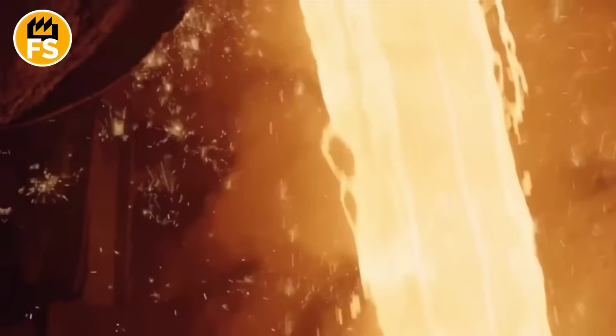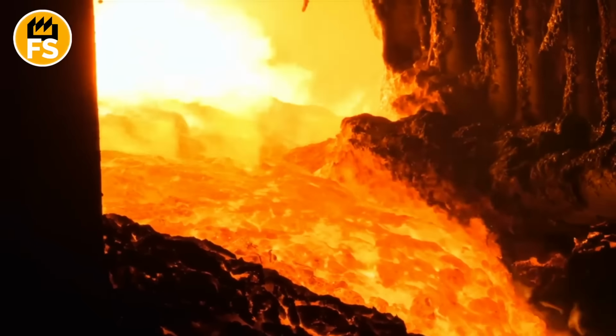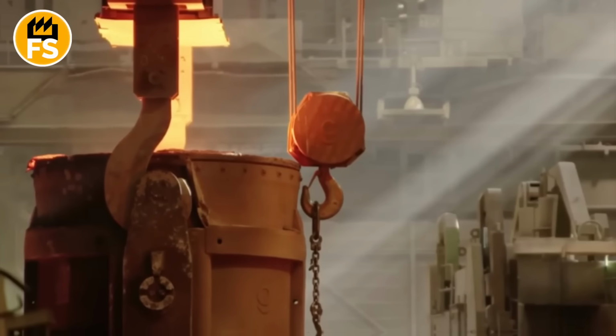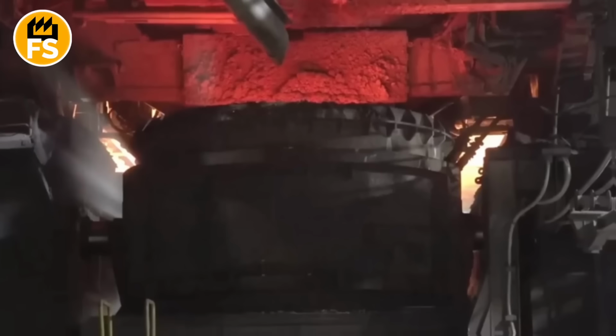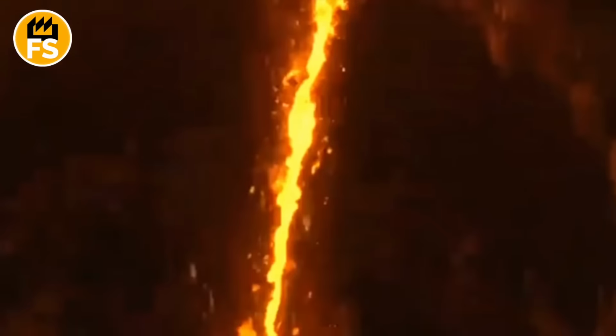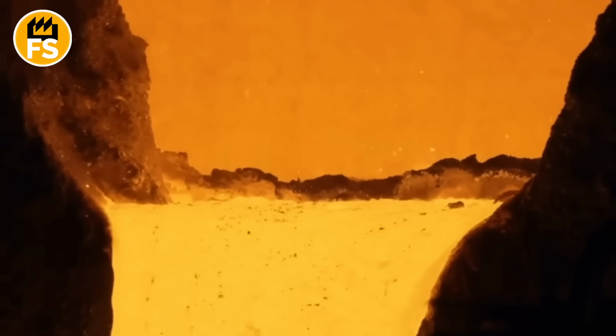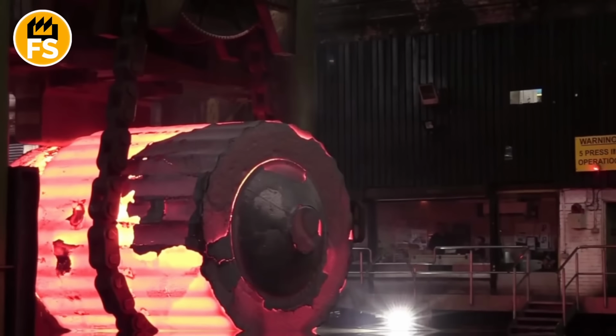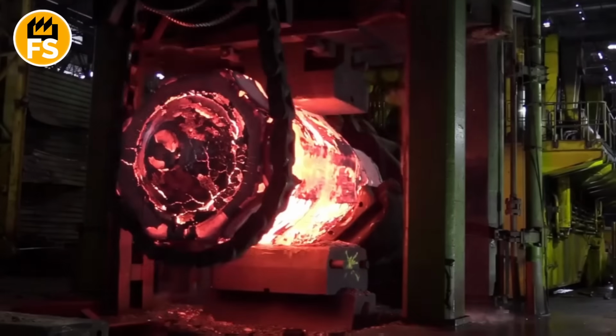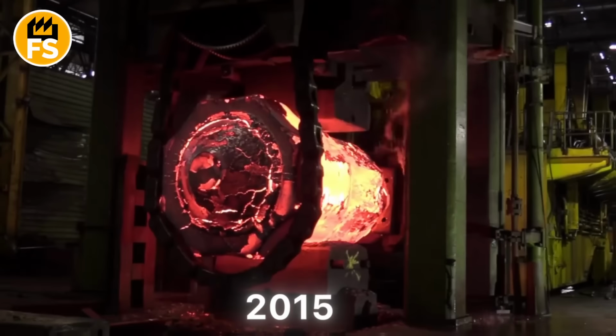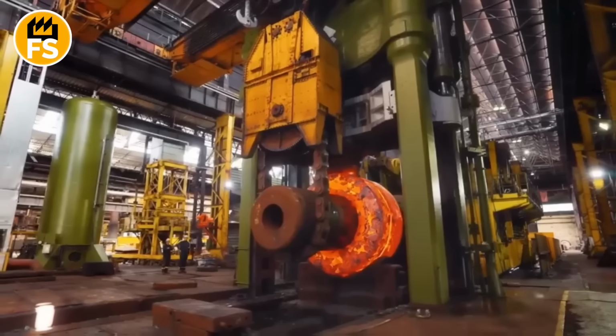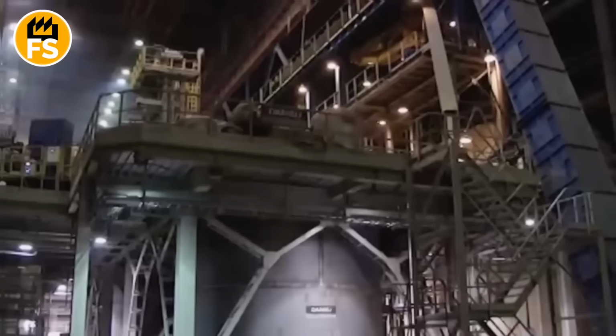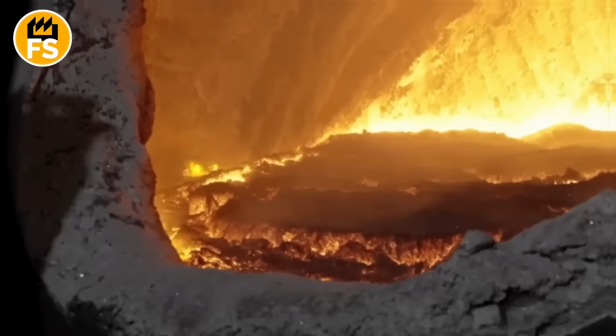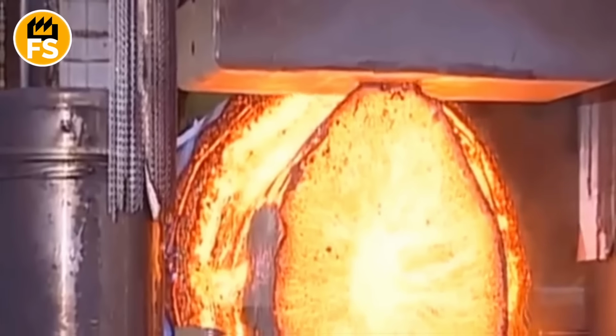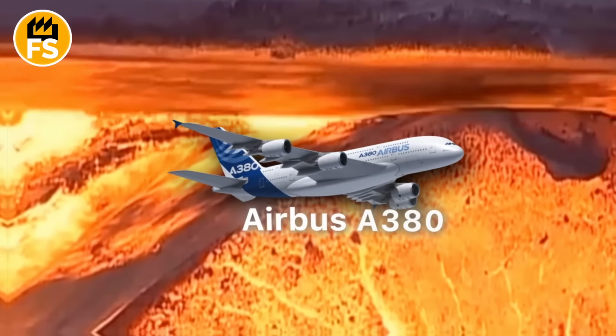It all starts in the foundry. To create a monolithic ingot, you need liquid steel of impeccable quality, poured into a mold in one continuous stream. This is a stage that demands maximum coordination, because we're talking about thousands of degrees and hundreds of tons of metal. A striking example of such an engineering feat was a record-breaking pour carried out by the British firm Sheffield Forgemasters in 2015. The company's metallurgists successfully handled the pouring of 607 tons of liquid steel into a giant casting pit. To put that volume in perspective, it's nearly the weight of a full-sized Airbus A380 passenger jet.